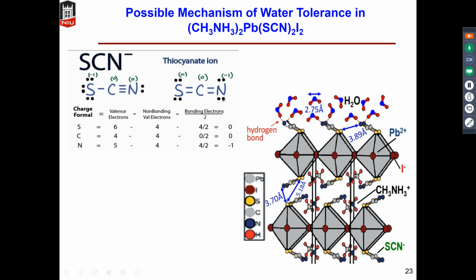to the terminal hydrogen, it actually blocks the entrance of additional water ingression. So this is a potential explanation of why this pseudo-halide-based perovskite thin film exhibited improved water stability or moisture stability.